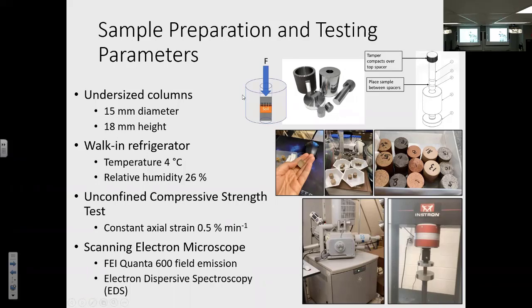And in order to mimic the environmental conditions, it was stressful, but we made these samples from scratch in a walk-in refrigerator at 4 degrees Celsius. I was wearing gloves, caps, boots, but I was in there. And then we cured them in a desiccator that I placed inside this refrigerator, because I don't know if you've been inside refrigerators, they are very high in humidity. So we wanted to make sure our humidity levels were also controlled. And so we used a desiccator to give us about 26% relative humidity.